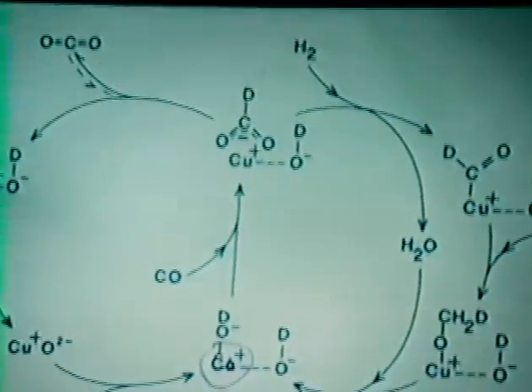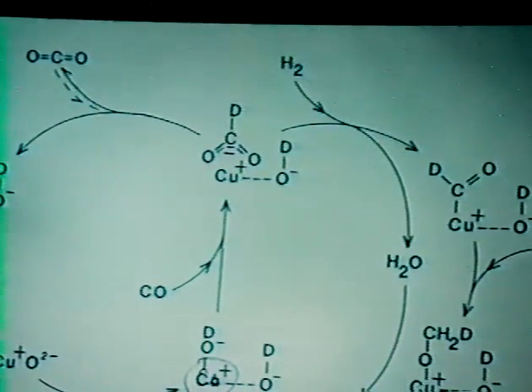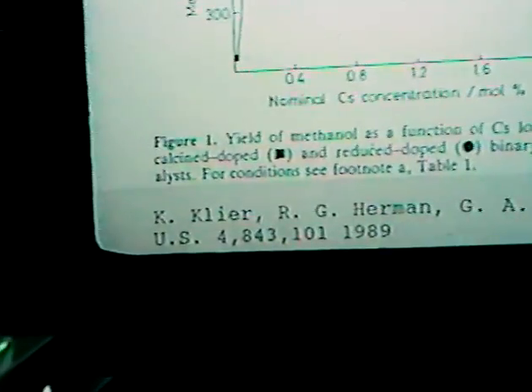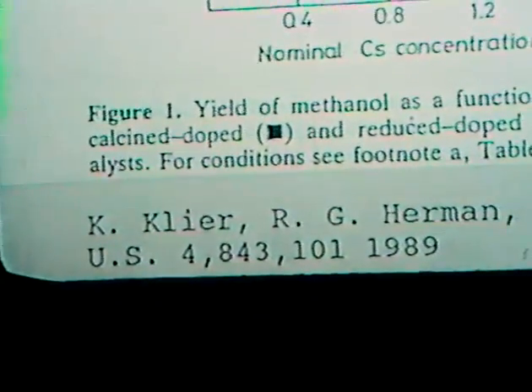The remaining two were coming from the unlabeled hydrogen. The promotion, and now you might say this is an academic play, and surely it was at the beginning, but we have this Office of Research at Lehigh University who wants us to patent things, and so we did so and were awarded the patent for methanol synthesis accelerated by heavy alkali, and the surface dopant does not have to be hydroxide, it could be formate, for example, because the hydroxides chew up the catalyst and so on.